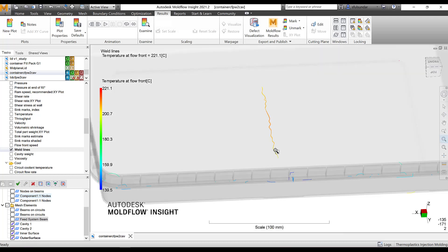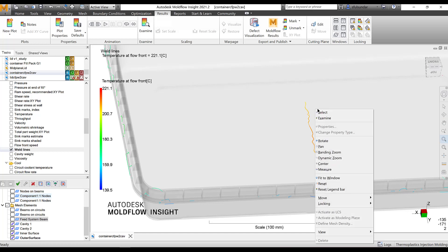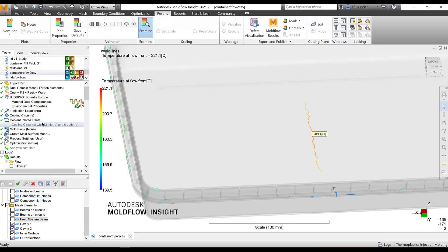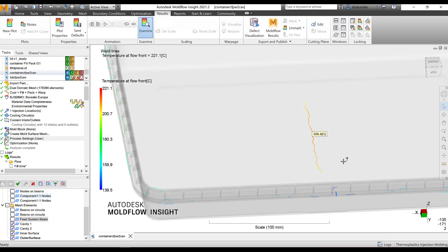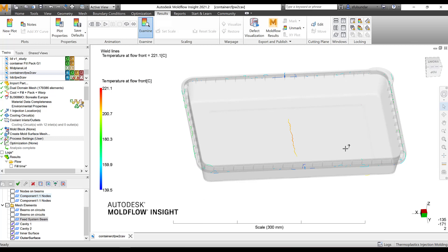Set it to pressure end of fill, temperature at flow front — hit OK, apply it. You should see that to make the weld line stronger, the weld line should not fall below 5 degrees from the melt temperature. That's a guideline — in plastics there are no hard and fast rules, only rules of thumb. In this case reviewing it shows 209, and the melt temperature is 240, so it has already fallen off too much. The weld line should not be below 235, but in this case they are all below that, so there is a possibility this weld line would be weak as well as visible.